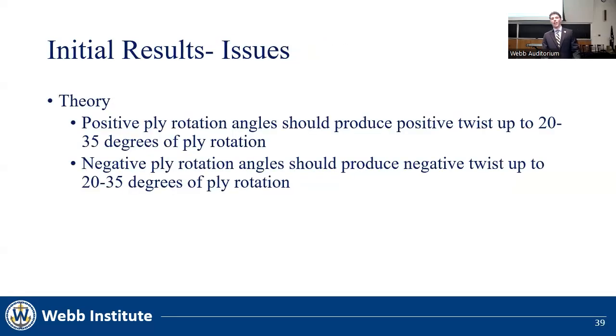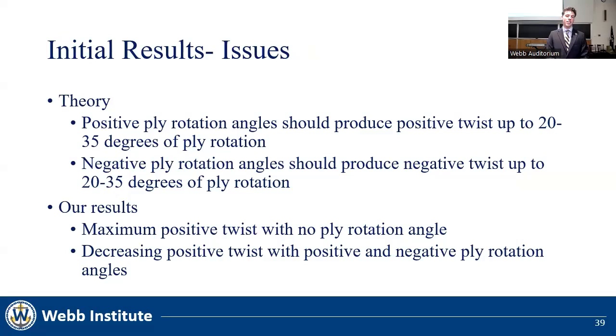These results do not align at all with the theory. In theory, a positive ply rotation should produce increasing amounts of twist up to a maximum between 20 and 35 degrees of ply rotation. A negative ply rotation angle should produce negative twist up to 20 or 35 degrees of ply rotation. At 0 degrees of ply rotation, the twist should be 0 or minimal. Our results, on the other hand, had a maximum positive twist with no ply rotation angle, and positive twist using positive and negative ply rotation angles at decreasing magnitudes.